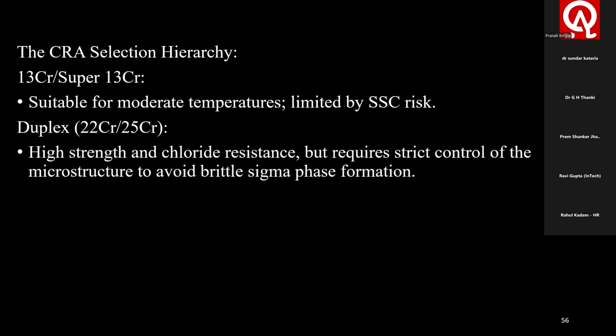Duplex: high strength and chloride resistance, but requires strict control of the microstructure to avoid brittle sigma phase formation. So welding plays a very important role. I have seen it with 2205, 2507 super duplex in industry, where casually the welder, without any advice from the supplier, hits the surface with the torch because they feel the moisture should be removed, and then goes welding. And they make this material as costly as gold within a few months in the structure. So this is very important.